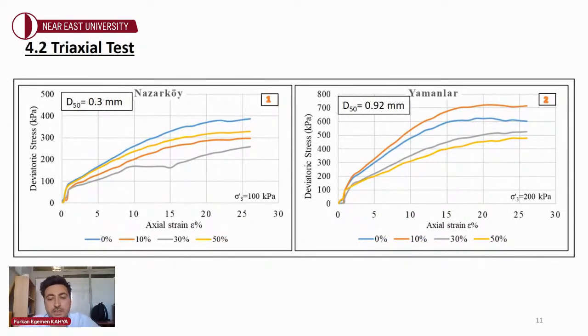The volume changes in sand exerted by fines content are not only important in terms of compressibility, they are also important in terms of shear strength, because any volume change in the soil contributes to the shear stress. Therefore, it is important to understand the fines content effects on the shear strength. If we look through the stress strain curves of samples from this standpoint, Nazarköy sand's shear strength decreases with an increase in mica content. Besides that, it shows a little increment at 50% mica content, but it is still lower than its natural form.